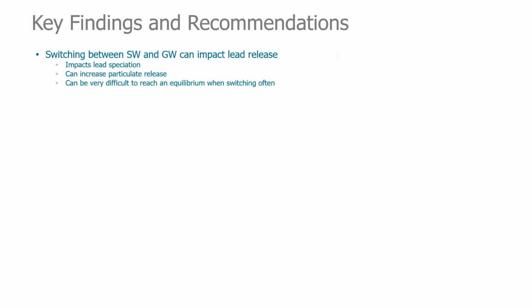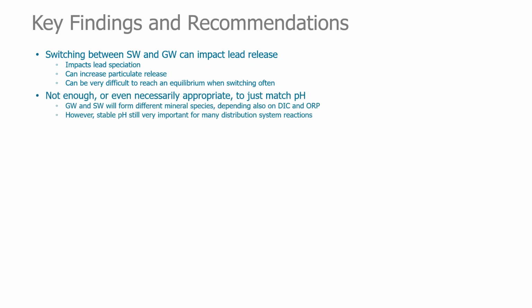So to summarize key findings and recommendations, switching between surface water and groundwater can impact lead release. It impacts the lead speciation. It can increase particulate release. We have to really understand that's important. It's very difficult to ever reach equilibrium if we're switching often. So wherever we can provide consistent supplies and avoid that switching is going to really benefit our corrosion scales.